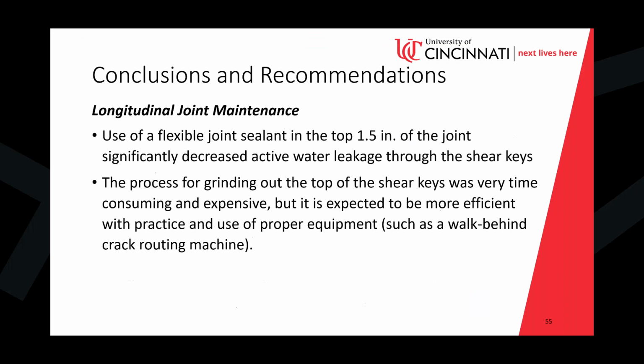With the longitudinal joint maintenance, we found that use of a flexible joint sealant in the top 1.5 inches of the joint significantly decreased the active water leakage through the shear keys. The process actually of grinding out the shear keys was time consuming and expensive, but it's expected to be more efficient with practice and the use of proper equipment, such as a walk behind crack routing machine.